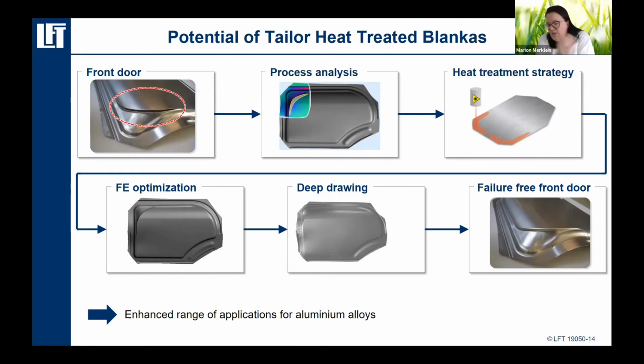If you use, for example, some optimization methods such as simulated annealing, you can transfer the results regarding the mechanical properties of the material to a temperature distribution that is necessary. And if you do so and you apply it to a sheet metal and you perform the drawing afterwards, you can see that you have a failure-free component. And so that was a real good success, leading also now to a transfer into industry.